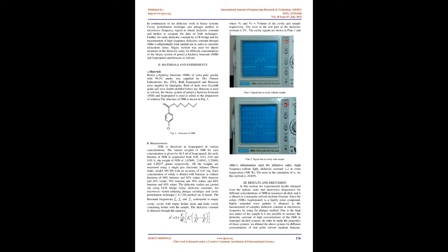Further, static dielectric constant measurements by LCR bridge and measurement of high-frequency dielectric constant through Abbe's refractometer were carried out in order to calculate relaxation times. The Higasi method was used for dipole moments in the dielectric study for different concentrations of the binary system of Pentyl P-Hydroxy Benzoate, 5-HB, and Isopropanol, with benzene as solvent.